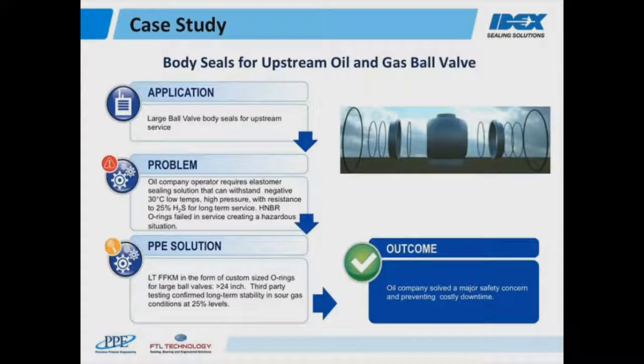Now the problem is that an oil company operator required an elastomer sealing solution for a valve that can stand minus 30 degrees C low temperatures, high pressures, with resistance to 25% H2S for a very long service. They already knew that HNBR O-rings had failed in service, creating hazardous situations. Now the PPE solution was to provide a low temperature FFKM in the form of customized sized O-rings for the large ball valves, which were greater than 24 inches. And we conducted third-party testing to confirm the long-term stability in sour gas conditions at the 25% levels. The outcome: the oil company solved a major safety concern and prevented costly downtime.